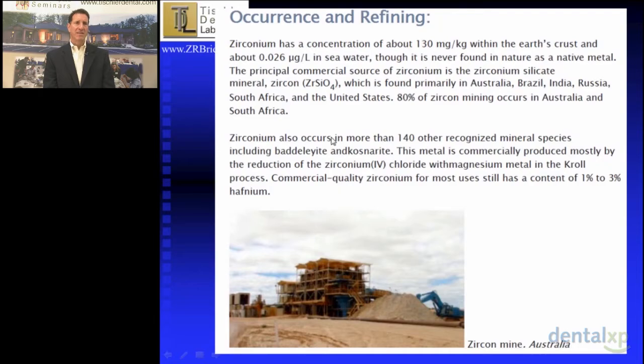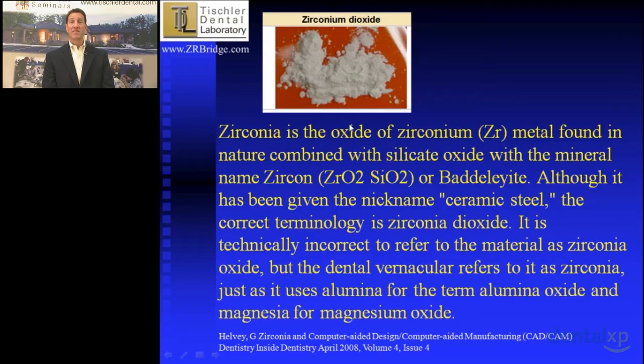What happens is the zirconium is mined throughout the world, and this mining of the sand product, basically, with zirconium in it, is then processed by a chlorination Kroll process that turns part of that zirconium into zirconium dioxide. This zirconium dioxide is the oxide version that is now used in dentistry. When you talk about aluminum, for example, that's really aluminum oxide, but we call it alumina, as we do zirconia, which is zirconium dioxide.